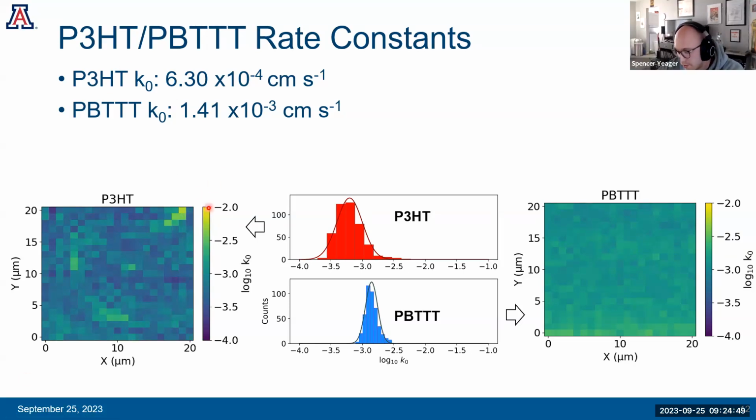You can characterize it doing similar electron transfer, except on a bare ITO, and you would get these kind of rate constants and make a similar map and see where it's fast and where it's slow. That's work that has been done before. There's a paper out about that, but that's one way you could get towards answering those questions.